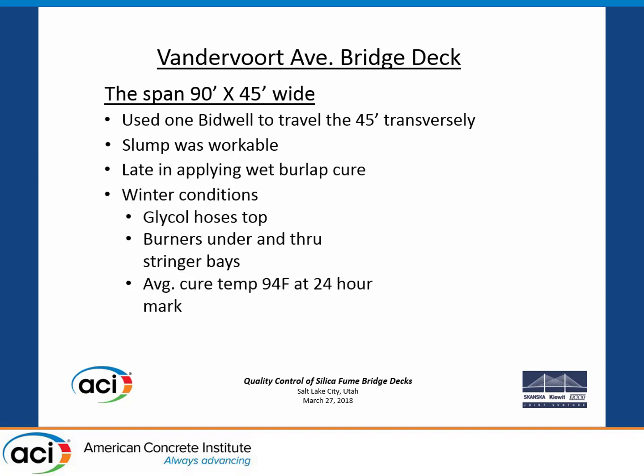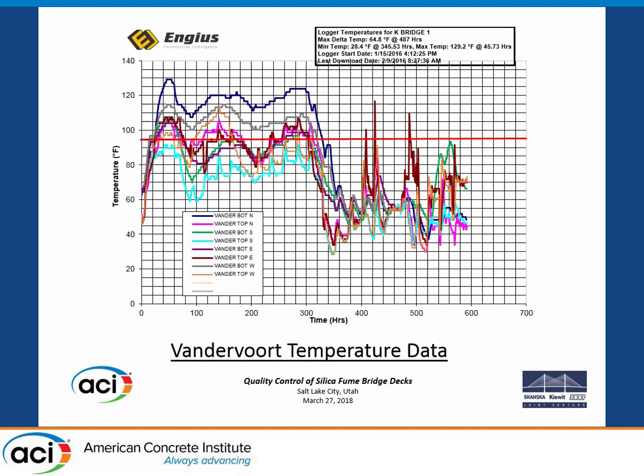Glycol hoses on top, burners under, and we're pumping it down through the stringer bays this time, because there's traffic on Vandervoort, and the average cure temperature is 94 degrees at 24 hours. All right, kind of too much of a good thing. So there we are. That's 95 degrees right across there. Cooking that deck.